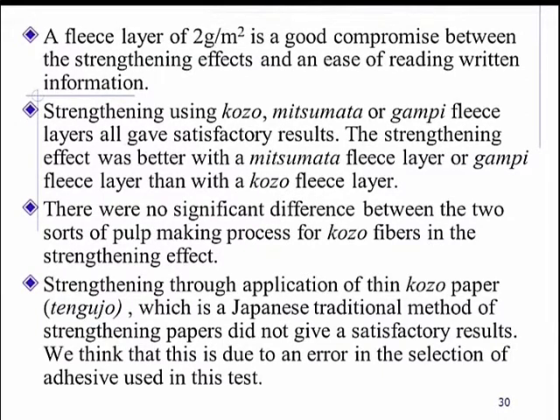There were no significant differences between the two sorts of pulp making process, Aarai and Akunuki, for kozo fibers in the strength effects. However, strengthening through application of a thin sheet of Tengujo paper with the Japanese traditional method of strengthening papers didn't give satisfactory results. We think that this is due to an error in the selection of adhesive used in this test.